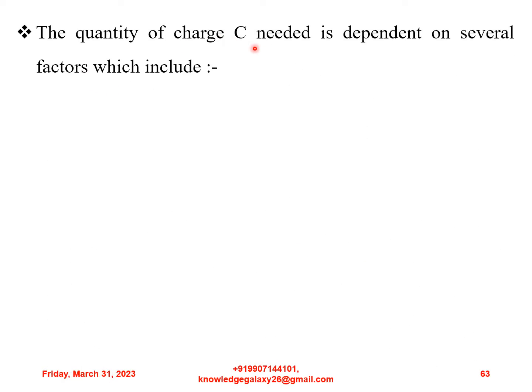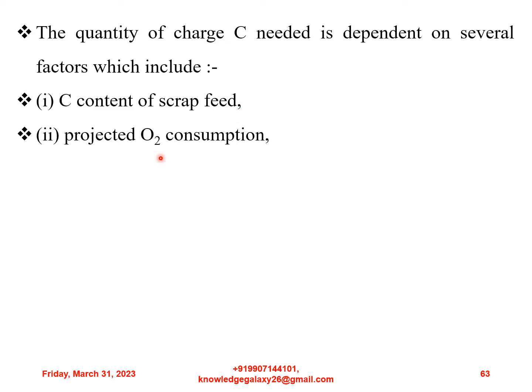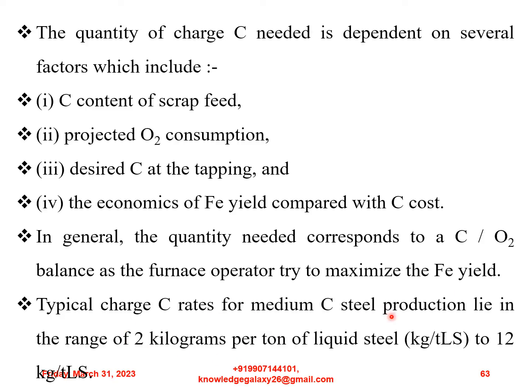The quantity of charged carbon needed is dependent on several factors, which include: first, carbon content of scrap feed; next, projected oxygen consumption; next, desired carbon at tapping; and fourth, the economics of iron yield compared with carbon cost. In general, the quantity needed corresponds to a C by O2 balance, as the furnace operator tries to maximize the iron yield. Typical charge carbon rates for medium carbon steel production lie in the range of 2 kg per ton of liquid steel to 12 kg per ton of liquid steel.